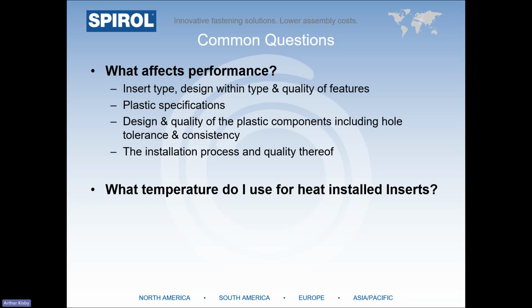In fact, there are many variables that impact insert performance within the application. Not only does the insert design, quality of the features such as knurls, barbs, and undercuts, but also the type of plastic. For example, an insert installed into nylon 6/6 with 30% glass fill will totally outperform the talc-filled polypropylene as it's much more rigid. The design and quality of the plastic molded part also plays a huge role in performance. Like, are there any knit lines in the boss surrounding the insert? Is the wall thickness of the plastic sufficient to handle the applied stress?